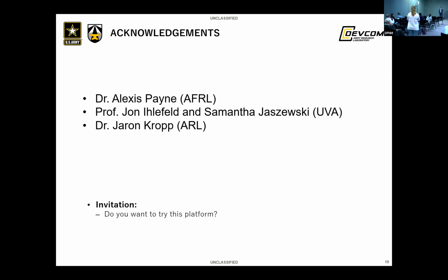Well, okay. I think melting is a feature, not a problem. It is just generally hard to work with, but having the heat that's generated during the pulse power events melt the gallium, I would say perfect. Select an alloy that is processable, but then in your application it is going to take heat from the system at that critical temperature as it melts. So this is EGaIn, I think, for most of this, but there's gallium-tin, you can get room temperature, sub-room temperature. Don't want to mess with mercury. But yeah, there are some creative things to be done on the liquid metal side there.